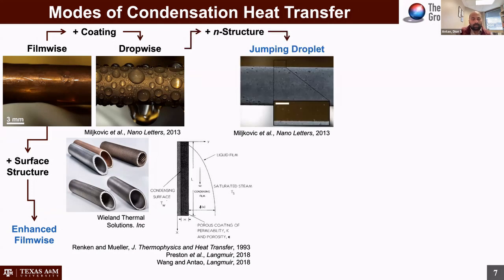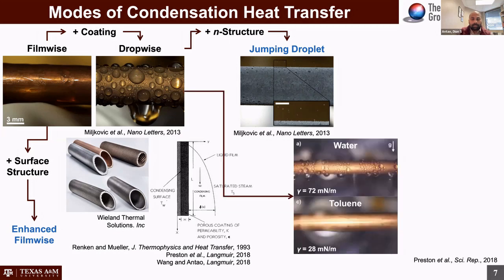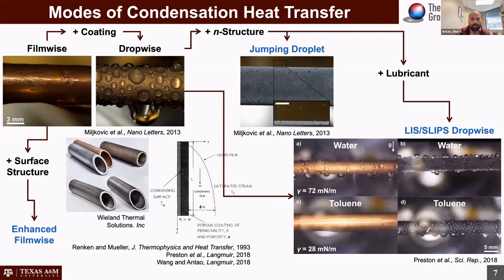You add nanostructures and coatings, and you can get this jumping droplet mode of condensation. But with any sort of coating, you typically cannot condense efficiently with low surface energy materials. And so if you use some lubricant material plus the nanostructures and coatings, you can get dropwise condensation in this LIS slips mode. And of course, the key aspect in all these condensation modes is the coating. The bulk of the presentation is going to be addressing the durability of that coating. And a small part of our presentation at the end will talk about design of these LIS surfaces, for the purposes of condensation or anti-icing or anti-fouling behavior, which exists at temperatures outside of the design temperature range.